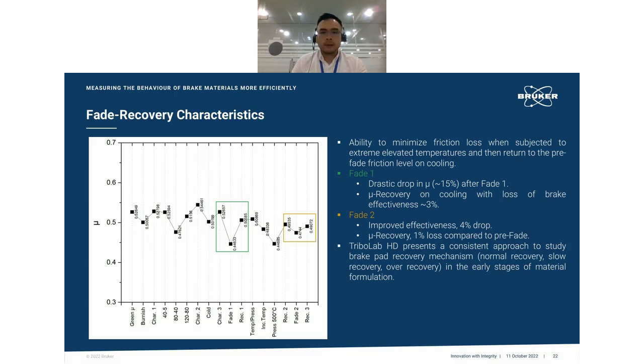So even within fade one itself, from the characteristic value 3 to fade 1, there is a drastic drop in the mu value of about 15%. But upon cooling, we get a recovery whereby the loss of brake effectiveness is only about 3% compared to pre-fade. So from 0.52 to 0.50 something. Yeah, it's about a loss of 3%, but it shows a good recovery trend.